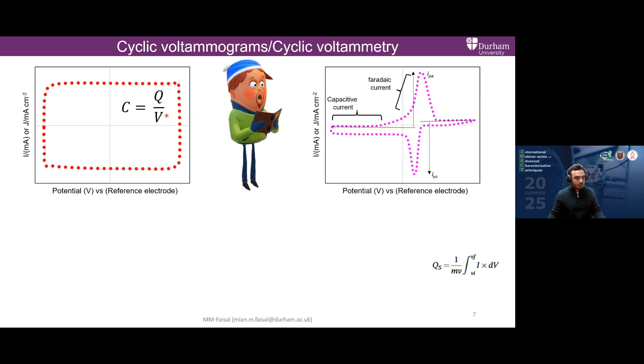What else can I still get from this one cycle, or whatever multiple cycles I've run? Because this is only one cycle, but I can run it at multiple scan rates, and the scan rates depend on your desirable application. If you need a very low scan rate, you can start from a very low scan rate and take it up to a higher scan rate, and then you can estimate the rate performance: what was the capacitance at the initial scan rate and what was its behavior when you take it up to a much higher scan rate. That gives you the rate performance, whether the material is very good when you are switching the potential very quickly, or whether it is very good when it is sweeping slowly between lower and higher potentials.